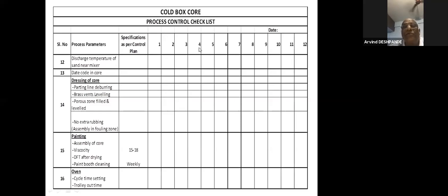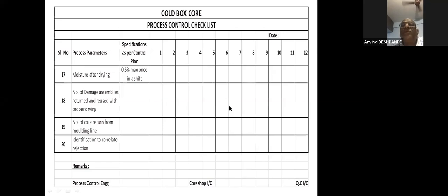Then trolley out time is also important, because after trolley out, everybody has to decide a time. After trolley out, after half an hour or 4 hours or 6 hours, the core should go into the mold. That's why trolley out time has to be maintained. Then moisture after drying of core, 0.5% maximum, once in a shift. It has to be done to ensure whether drying is proper or not; this is most important.